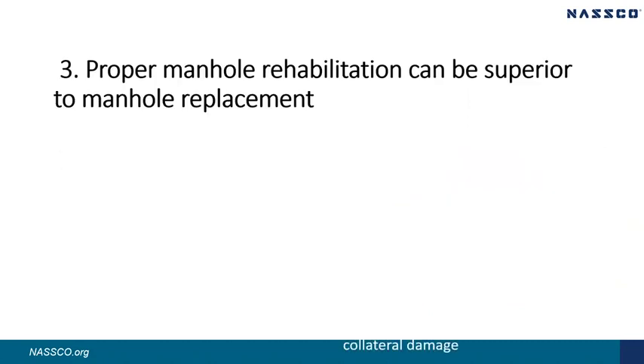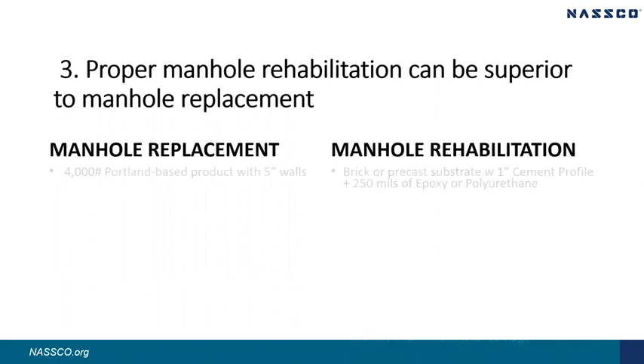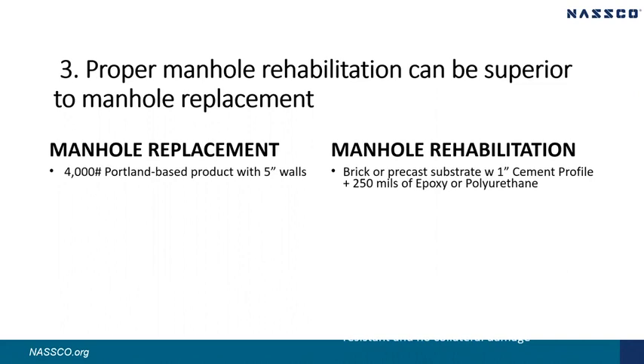Point 3, when making a replace or rehabilitate decision regarding a manhole, we often think that it would be best if we could just replace the manhole. However, proper manhole rehabilitation can be superior to manhole replacement in many cases. Let's compare replacing the manhole with 4,000-pound Portland-based precast sections versus spraying the existing brick or concrete manhole substrate with 1 inch of engineered cement profiling material and then topping it with 250 mils, i.e. a 1/4 of an inch, of either a polyurethane or an epoxy.